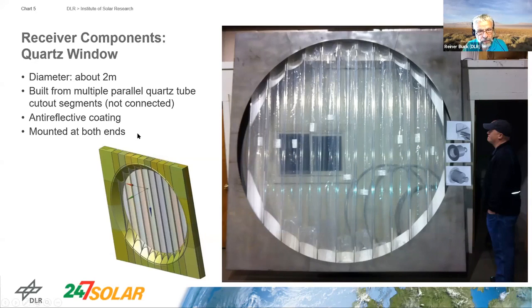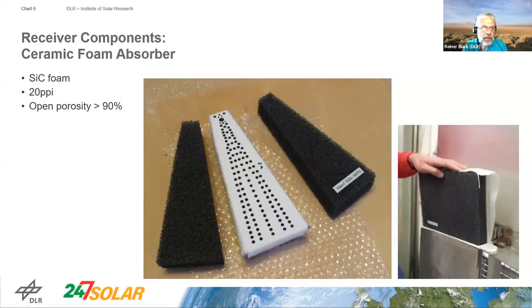It is equipped with an anti-reflective coating, which helps to avoid the reflective losses which typically occur on quartz windows. And it's mounted, as you can see here, on both ends. We have ceramic structures which keep the quartz segments in place, but allowing for some flexibility and some movement to avoid stresses. The other important component is the ceramic foam absorber. It's built from silicon carbide foam, and it has a pore size of 20 ppi and an open porosity above 90%. That means the struts of these ceramic foams are very thin, and we have quite effective convective heat transfer in these structures.